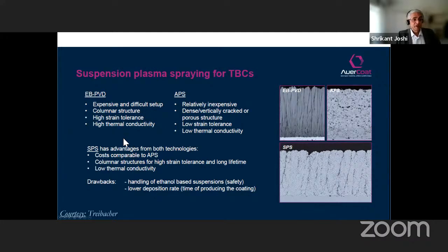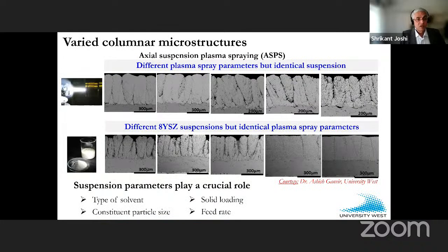It's much cheaper than EBPVD. It yet provides a columnar structure. It has potential to develop coatings with low thermal conductivity, and let me just say that you have a wide choice of suspension media now available, although most early work showed that if you are to target a columnar coating, you would have to use ethanol as a medium, which the industry does not necessarily like. There were also, as I mentioned, some reservations about deposition rate, but I'll show you that that was passed.